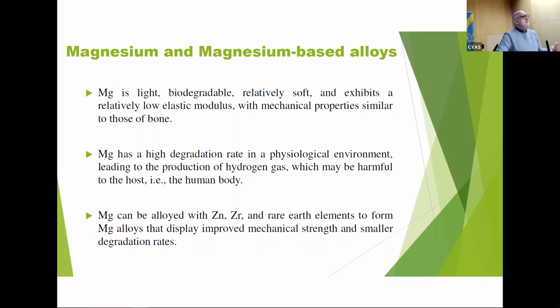In comparison, magnesium is light, soft, and has good mechanical properties similar to our bone, almost the same. But the problem of magnesium is the degradation rate. It degrades very fast once inserted in the human body because it's very reactive. We have to stop this reactivity to make a good recovery after surgery. So sometimes they use some kinds of alloy to increase the corrosion resistance of magnesium and to delay its corrosion also. But still now, no concrete results about the coating to resist the corrosion.